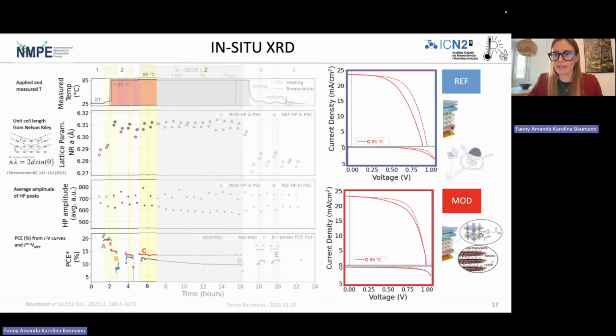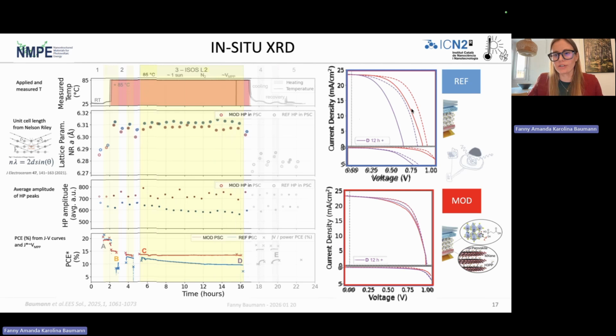And in the reference, we have that only on one side. So in this case, we believe that it's more the fact that this is a very large strain at the interface in the reference that would not be as present in the modification. Okay, moving along, we see that during the time, there's a large development of inverse hysteresis and also a voltage drop in the reference cell, while in the modification, well, there's still inverse hysteresis, likely because of an increase in ionic conductivity, but we do not see any evolution of this inverse hysteresis.